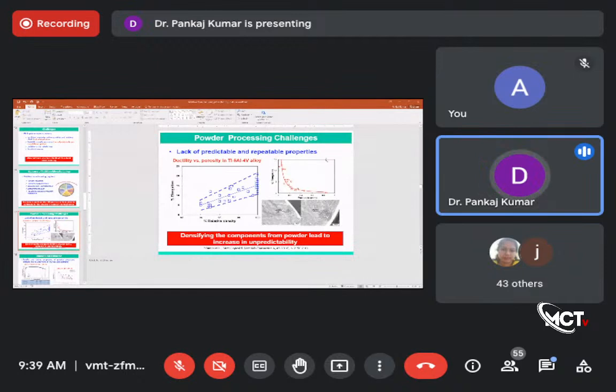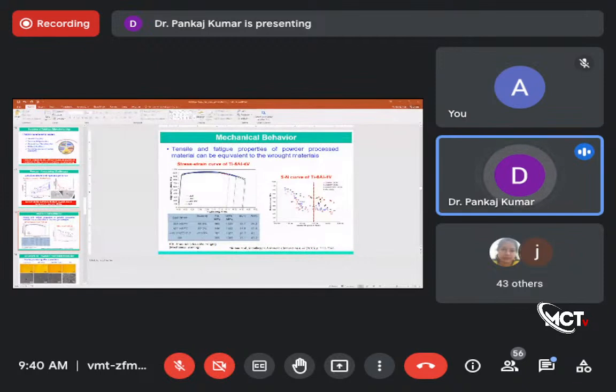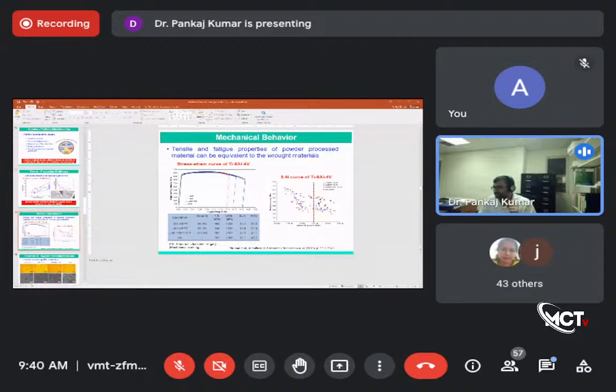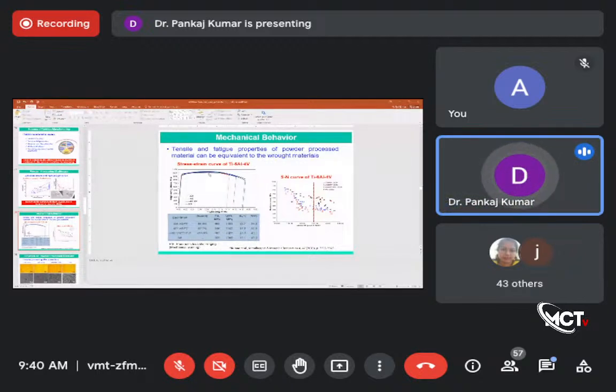Can we change that? Or can we control it? Yes, we can, but not during the additive manufacturing process, but after that, right? So you can in fact control the performance by doing post-processing. You can control the powder process parameters, and you should be able to get the properties you need. For example, here you see you have different powders and different processes, and you have different properties altogether, right? You see the stress strain curve, different powders, different processes, you are able to achieve properties very close to the state of the art mill annealed conditions. So you see this table, it clearly shows that behavior.